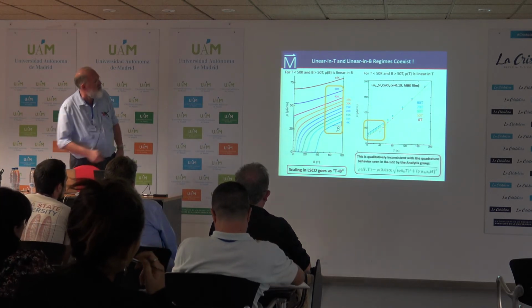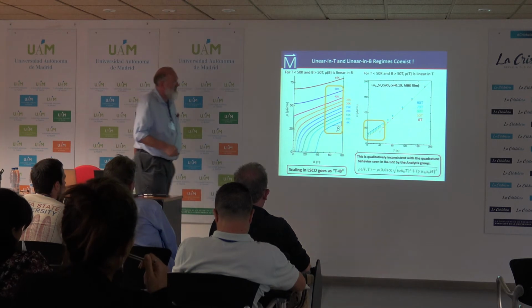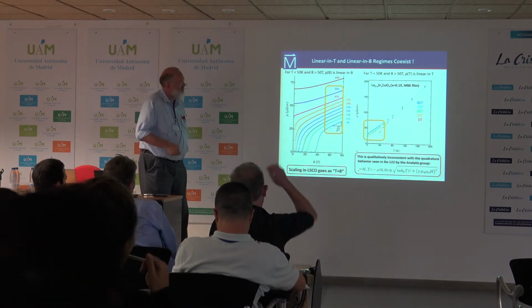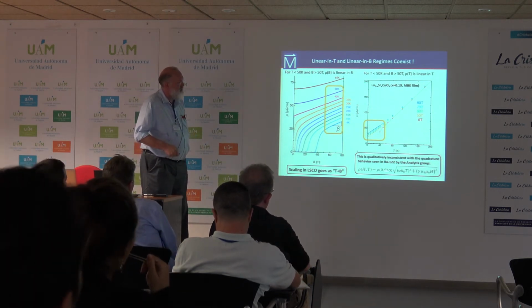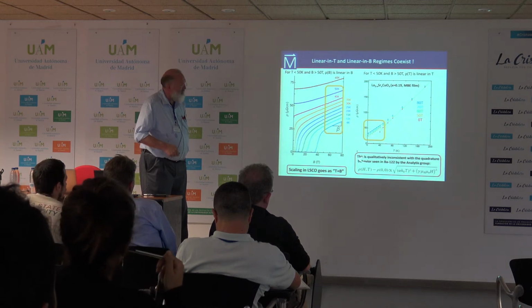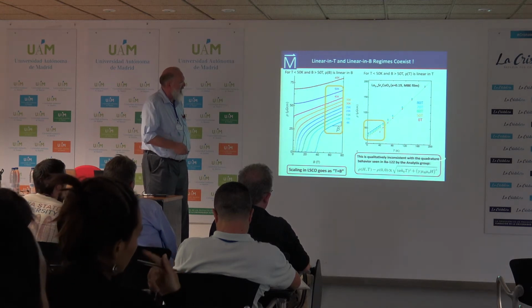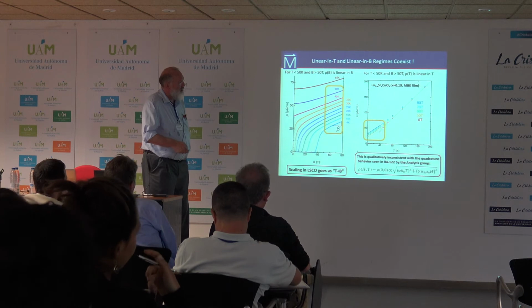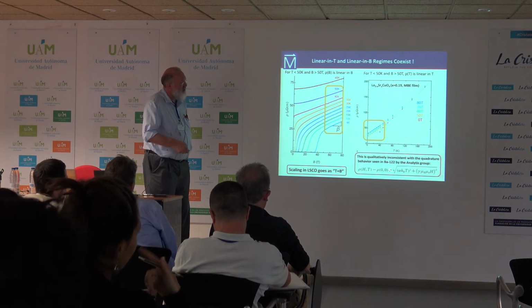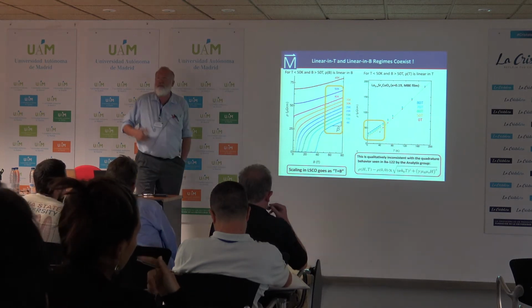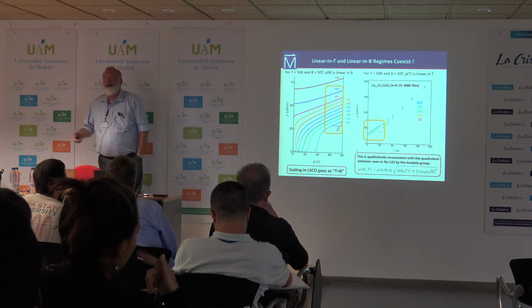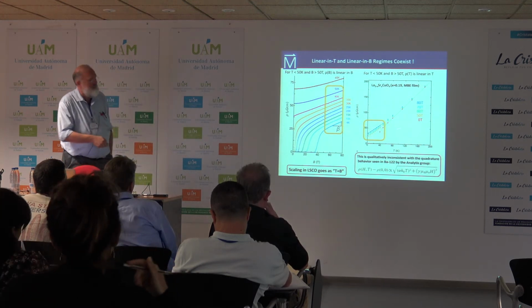And that is in striking qualitative inconsistency with the quadrature behavior seen in barium 122. It's clearly observed in that system. It's an experimental fact. We don't know why it's different. But with this kind of adding in quadrature, you will never get a regime where you're linear in both B and T. And we clearly see that here.